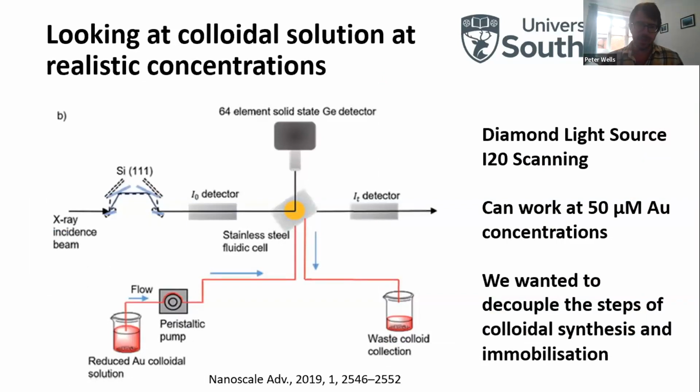So that was work from Scott Rogers. And then with George Tierney, we tried to follow that by looking at these materials in solution on the beamline. What we wanted to try to understand was the importance of the immobilisation step. We really wanted to assess the colloid solutions at the concentration we typically make them at, which is very low concentration, typically around 50 micromolar. And that's a real challenge. Trying to get EXAFS data on such dilute systems is very difficult.